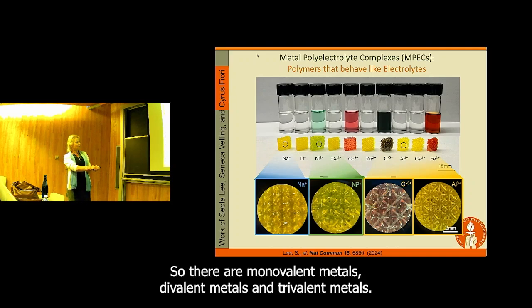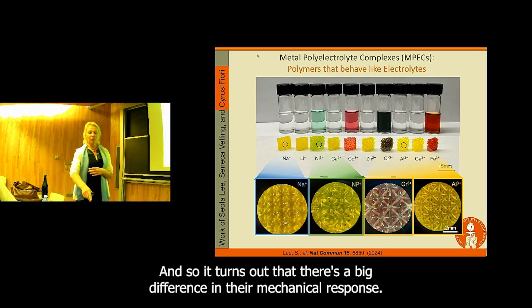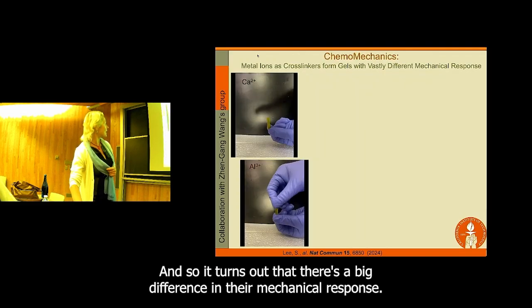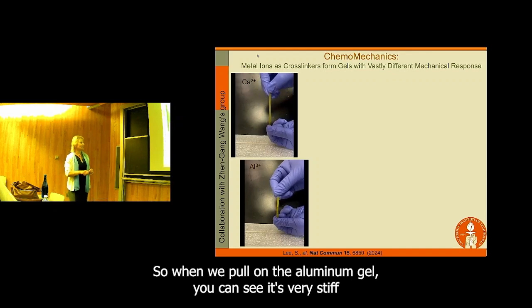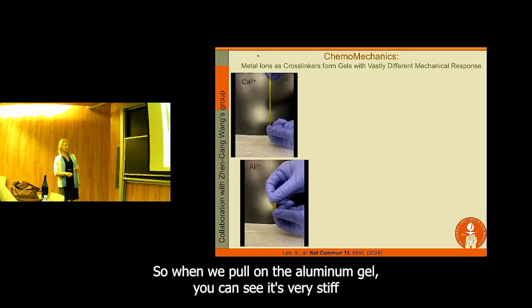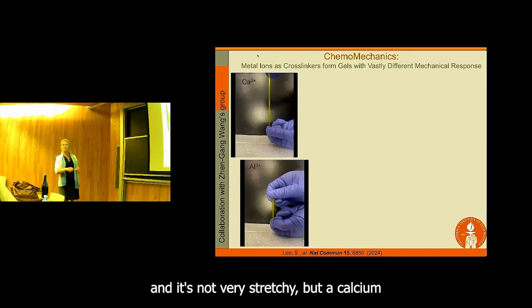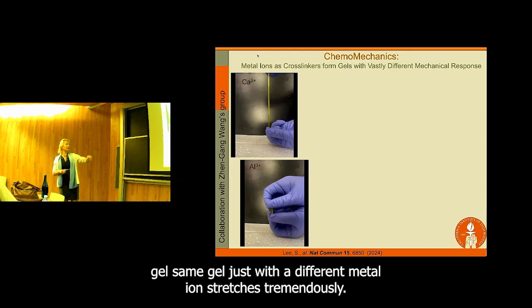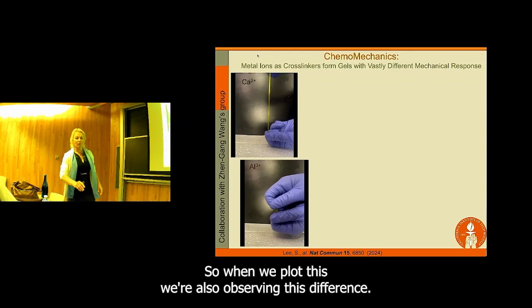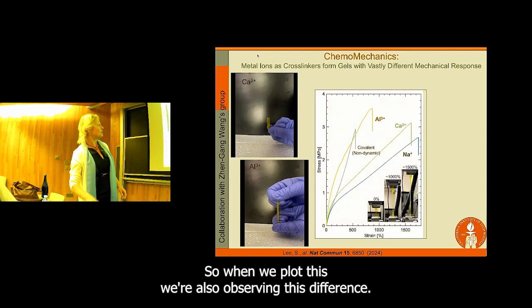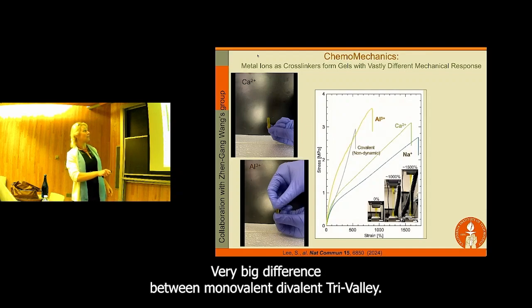So there are monovalent metals, divalent metals, and trivalent metals. And it turns out that there's a big difference in their mechanical response. When we pull on the aluminum gel, you can see it's very stiff and it's not very stretchy, but a calcium gel, same gel, just with a different metal ion, stretches tremendously. Right? So when we plot this, we're also observing this very big difference between monovalent, divalent, and trivalent.